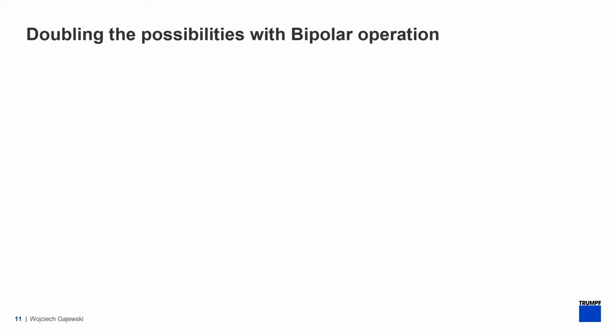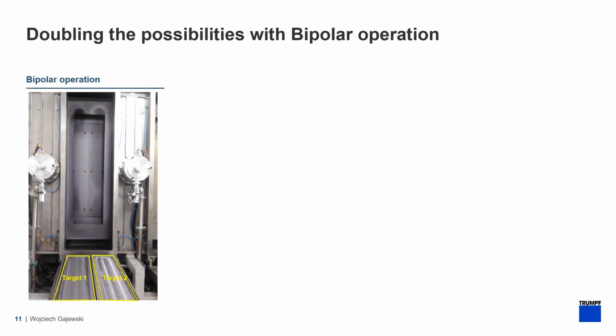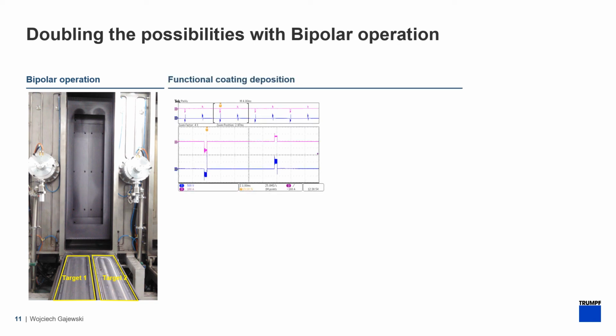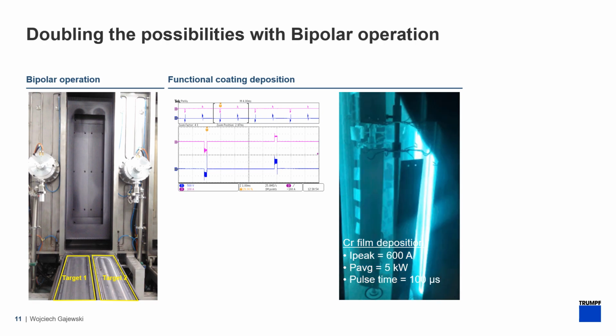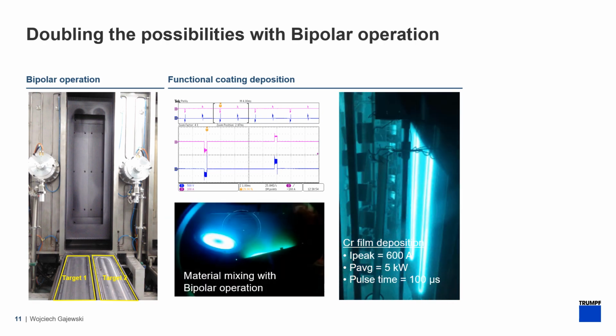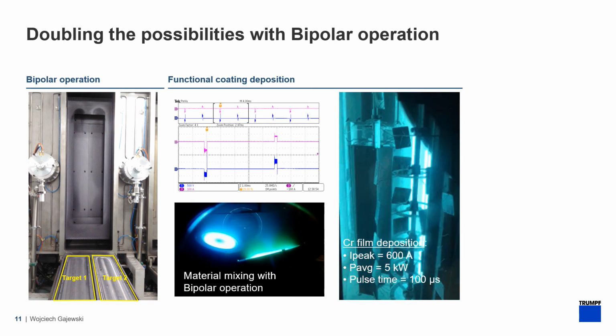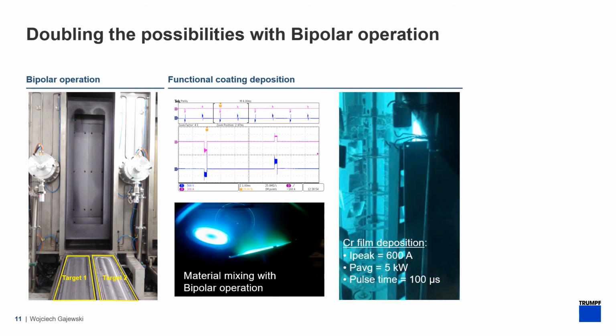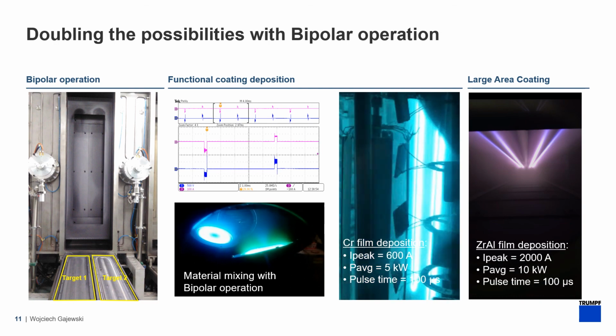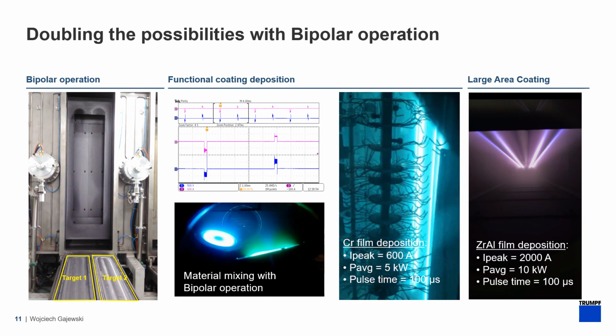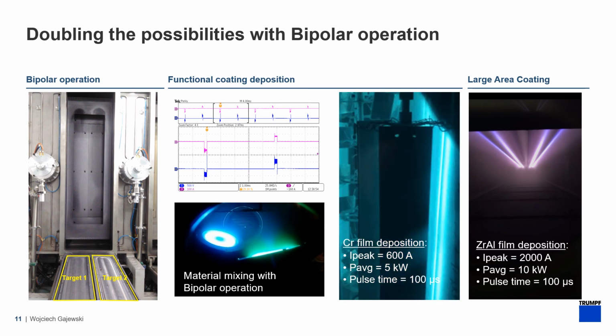Another advantage of having a controlled current during the HIPIMS pulse is the possibility to enter bipolar operation. Many industrial systems operate with dual magnetrons, both planar and rotary magnetrons. Those systems need HIPIMS which can work in a bipolar operation mode, as MFs or bipolars which are known in this community. So we can not only improve the quality of the coating by introducing HIPIMS, but we can also enter the possibility of material mixing with bipolar HIPIMS operation. And the ultimate goal would be to finalize the testing in large area coating, where HIPIMS can also be applied, for example, in some low-E coating business.